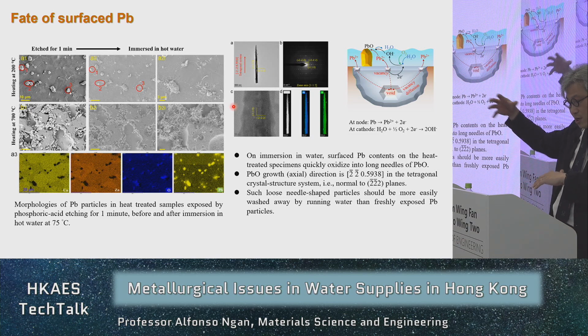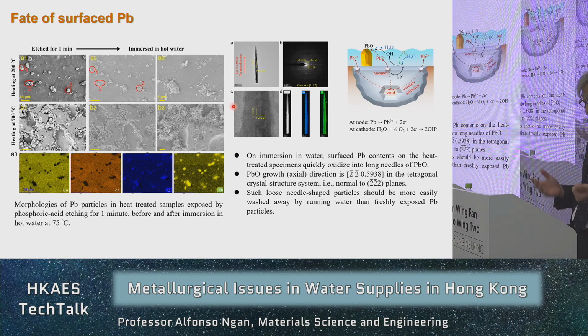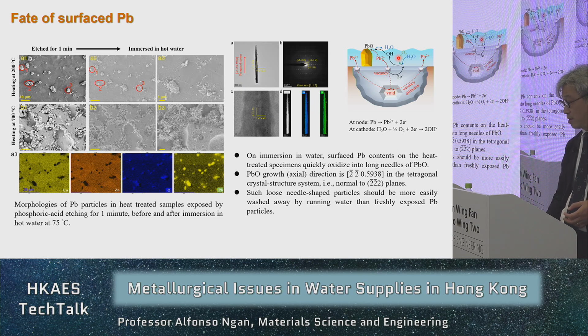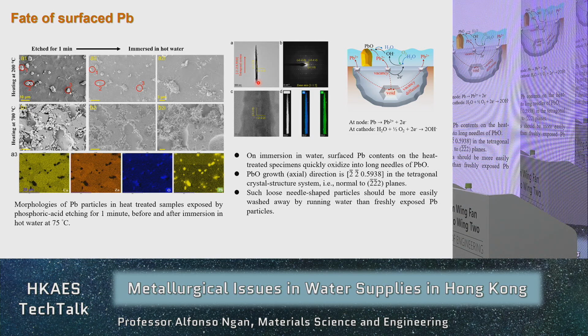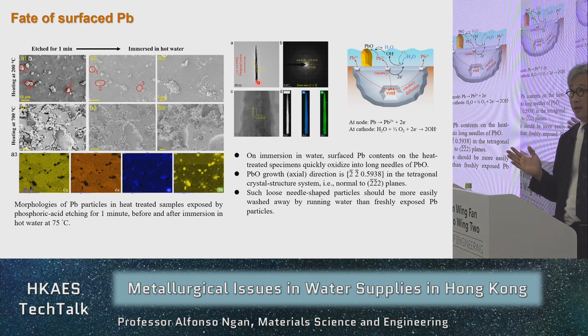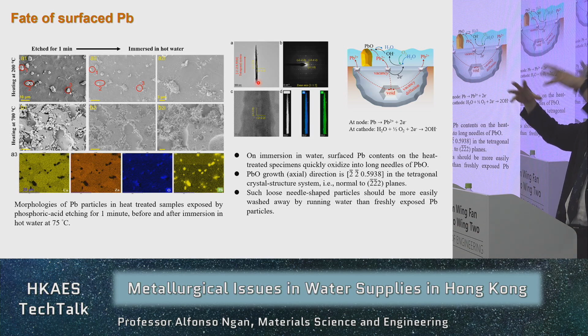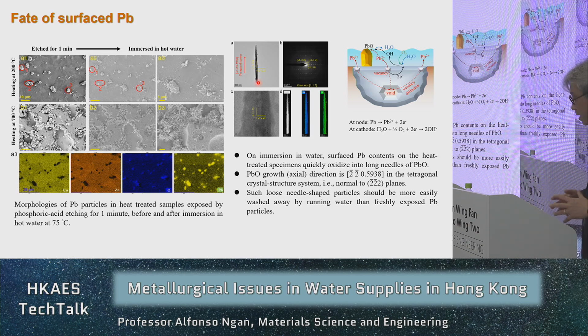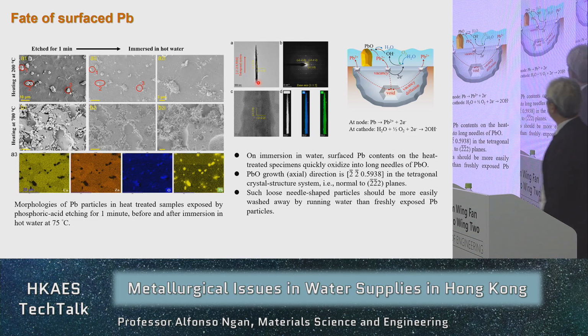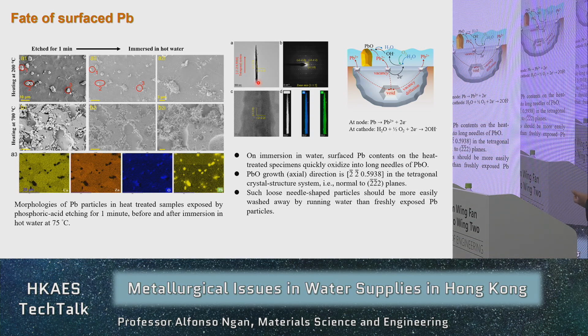So the lead now comes out after heating, and what is the fate of that? Well, the lead that has come out will quickly react with the surrounding water. We're immersing the sample into water to study this leaching, and the lead oxidizes to become lead oxide. The interesting thing is that sometimes these lead oxides become a sharp needle sticking out. So the growth of the oxide is highly anisotropic. It's not like a smaller ball growing into a bigger ball, but highly anisotropic along a certain crystallographic direction, which is this direction. And of course, the needle cannot stand the current if the water is drifting around, so the needle would break, and that is what is causing the leaching.